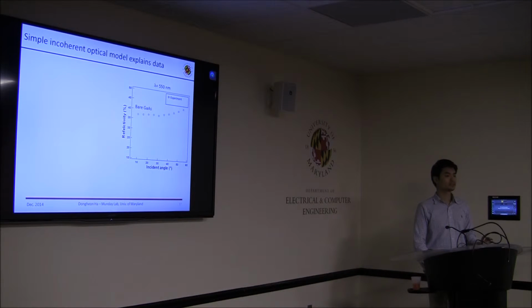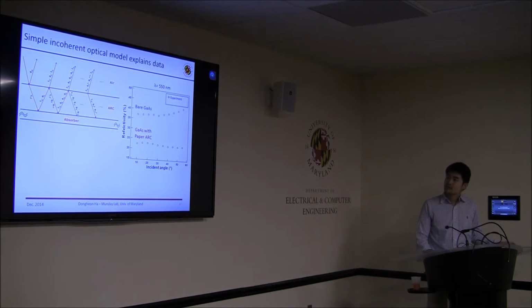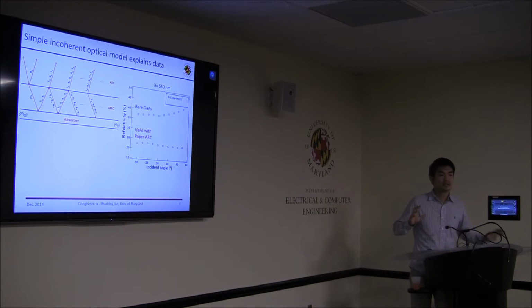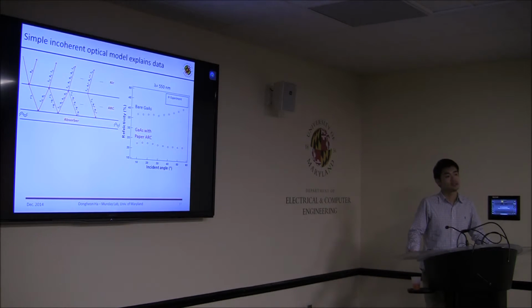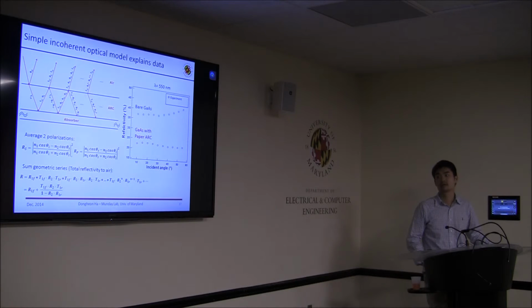So I wanted to understand the enhancement in a more detailed way, so I developed an optical calculation model. We assume that we have three different layers: air, our ARC, which is the transparent paper, and our absorber, which is gallium arsenide. To calculate the total reflectivity to air, we need to consider the multiple reflections, and the total reflectivity to air can then be calculated based on a geometric sequence.